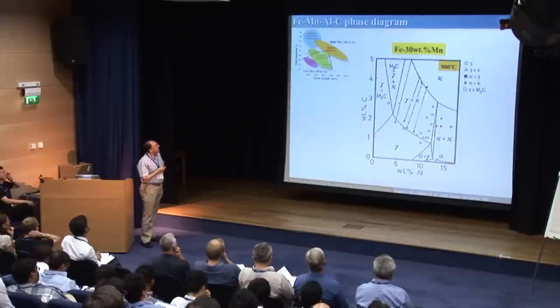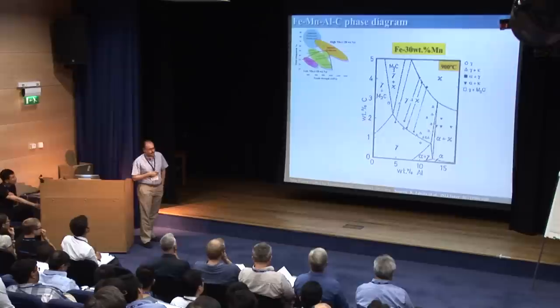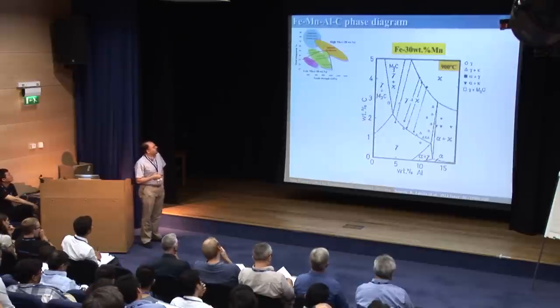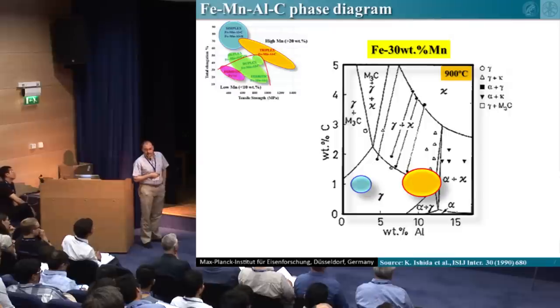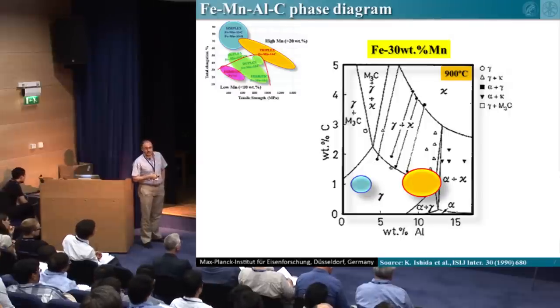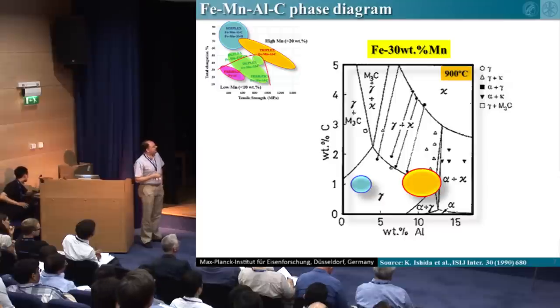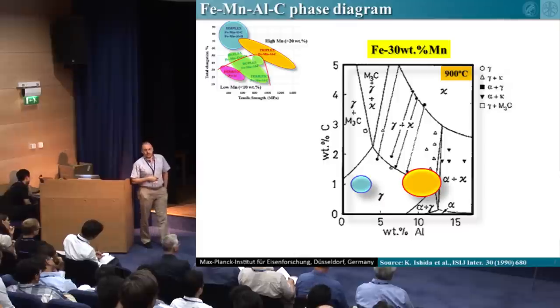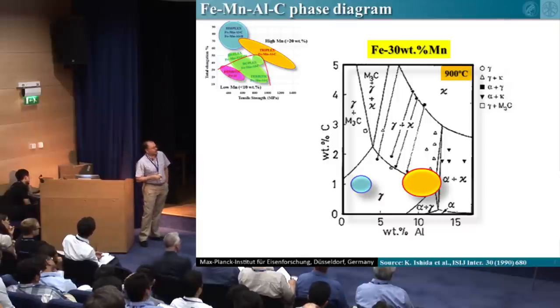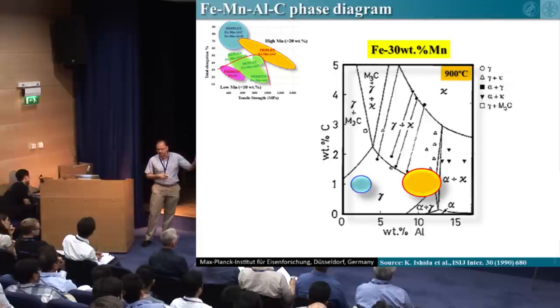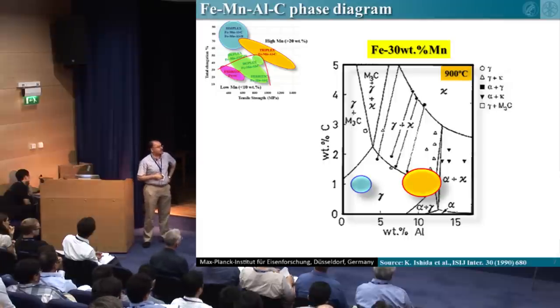And if we take a look at the iron-manganese-aluminum-carbon phase diagram, which was done 20 years ago, if we look at iron with 30% manganese, this is the simplex, pure austenite, nothing new. But as soon as we add more aluminum, we are going in this direction, where the kappa phase is formed. And also, as you can see here, even ferrite. Today, I will not talk about the formation of ferrite because this is mainly formed at grain boundaries.